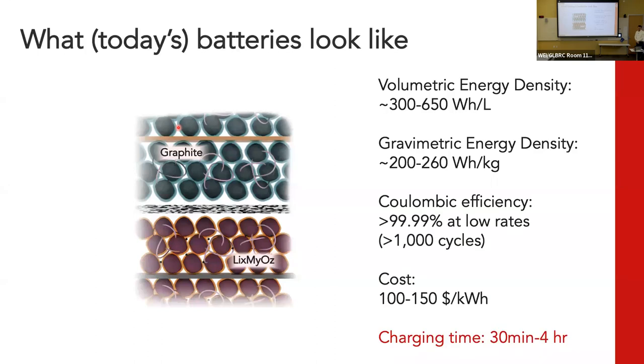But this gets us to the current state of the art, where we have a pretty good volumetric energy density compared to everything that came before lithium. Something like 500 watt hours per liter is really good these days, and 250 watt hours per kilogram for gravimetric energy density. One of the key things about lithium-ion batteries is this coulombic efficiency. You can cycle this thing back and forth over and over again, more than 1,000 times in many cases, because there's not much irreversible side reactions going on at either electrode in these optimized systems.